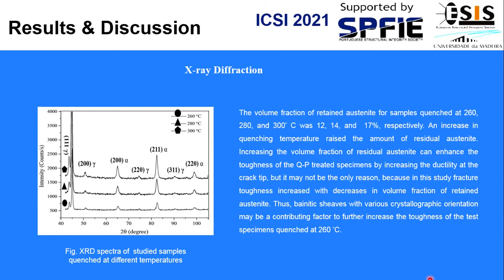Thus, bainitic sheets with various crystallographic orientations may be a contributing factor to further increase the toughness of the test specimen quenched at 260 degrees Celsius.